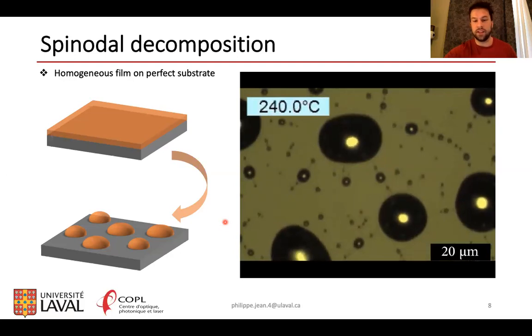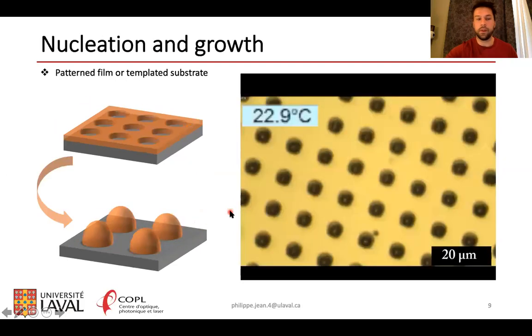Yeah, and you notice that these islands or droplets are of different size and shape and of pretty much random arrangement on the substrate. So the second mechanism at play in dewetting is nucleation and growth. In this case, if you start from a patterned film or a templated substrate, you can actually control the size and shape of the resulting droplets after dewetting.